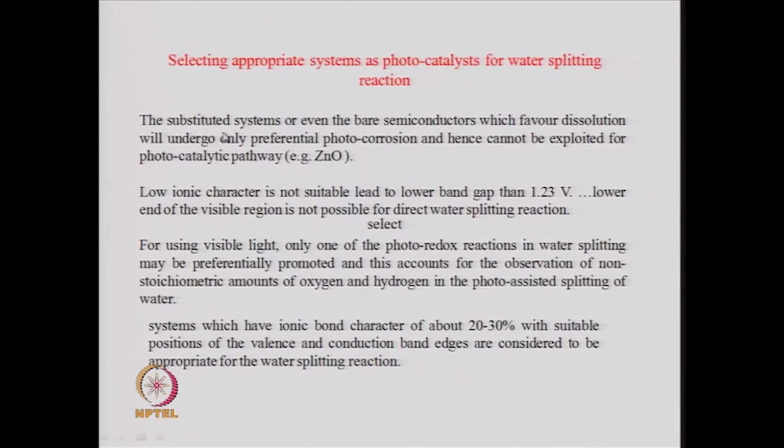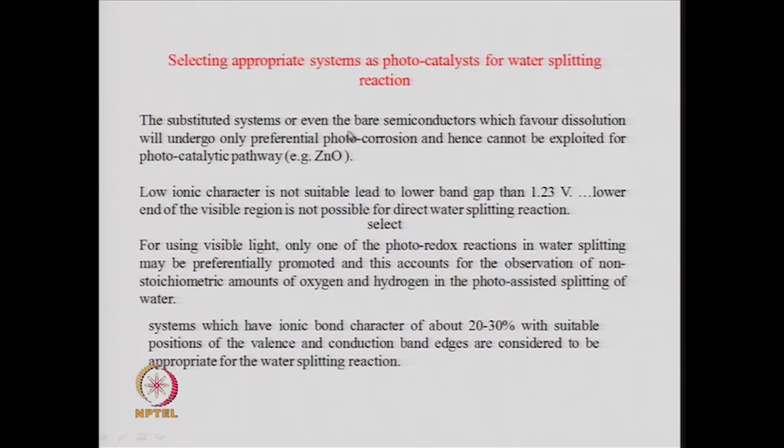However, if you have systems which favor dissolution, then only preferential photocorrosion will occur and they cannot be exploited for the photochemical splitting of water. And this is an example of zinc oxide, where it cannot be used for photoelectrochemical splitting of water due to its preferential photocorrosion.